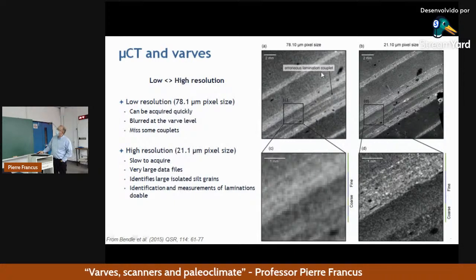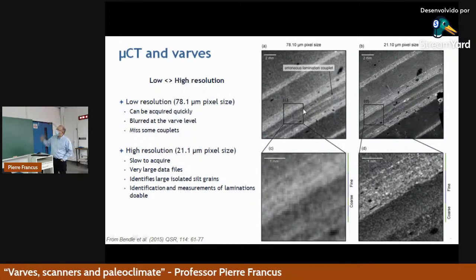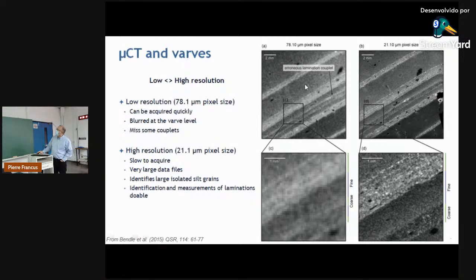Here's just to give you an example. This is a scan made in a laminated sediment with an 80 micron resolution, and here at 20 micron resolution, you can see really the difference between the two, where you can distinguish the limits, the boundaries of the laminations.